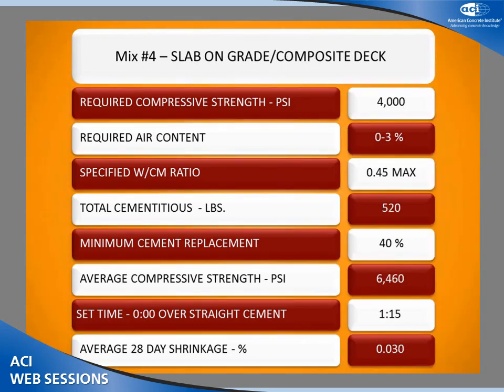Slab on grade, slab on metal deck, down to 4,000. Total cementitious back down to 520 at a 0.45 water-cement ratio. At the end of this presentation, I'm going to tell you about the research project that we did with the Minnesota Concrete Council, which even takes these numbers down lower. And I'll conclude with that.